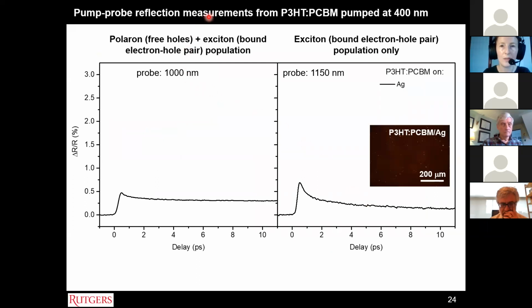So the pump probe reflection measurements that he carried out were of the polarons and excitons in a P3HT:PCBM blend. So that's the typical bulk heterojunction photovoltaic layer used for prototypical conjugated polymer-based photovoltaic devices. They were excited at 400 nanometers, and then to probe the polaron and exciton population together, the probe wavelength was set at 1000 nanometers, and then to probe just the exciton population only, he probed at 1150 nanometers.